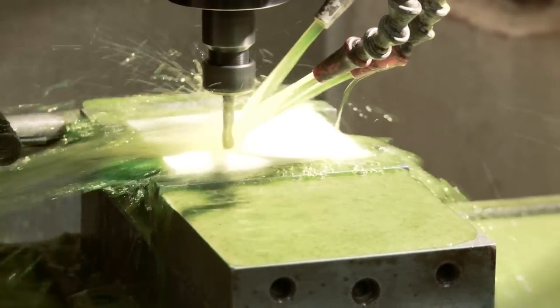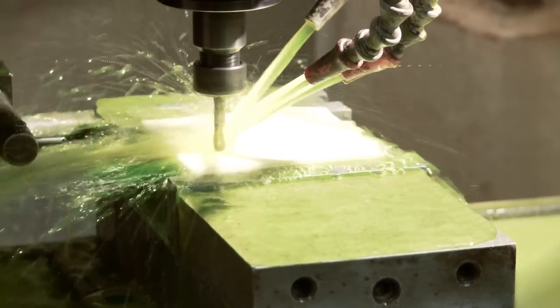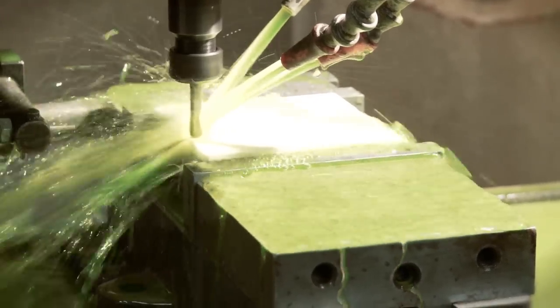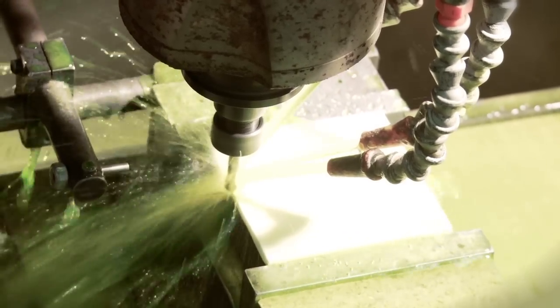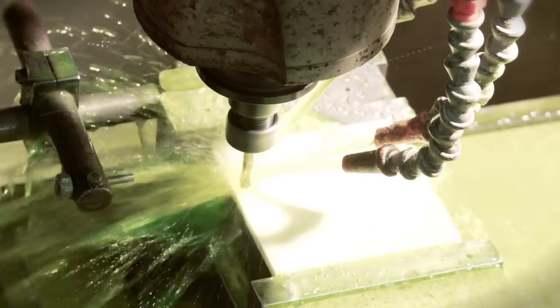When milling Macor, a cutting speed of 20 to 35 surface feet per minute is suggested with a chip load of 2 thousandths inch per tooth. The suggested depth of cut is 150 to 200 thousandths of an inch.